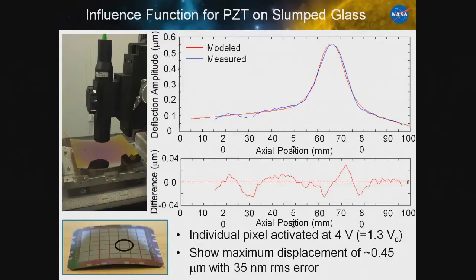You see a bottom electrode, the magenta color here is the lead zirconate titanate, and you see an array of centimeter square top electrodes on this part. And what is very difficult to see is that from each one of these electrodes, there are traces that come out to the side that allow us to electrically address each one of the elements.